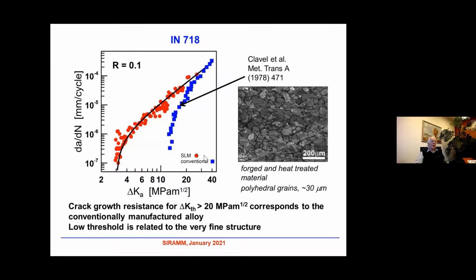And now, if we compare our data on Inconel produced by selective laser melting, this curve, with conventional data, very old data published nearly 50 years ago on conventional material, we can see there is a big difference. Practically the same behavior we have here for the highest rates, because the mechanism of crack growth by means of striations and so on is identical. However, in the threshold values, this material produced by additive technology is definitely much worse.